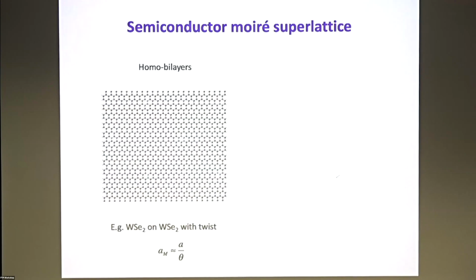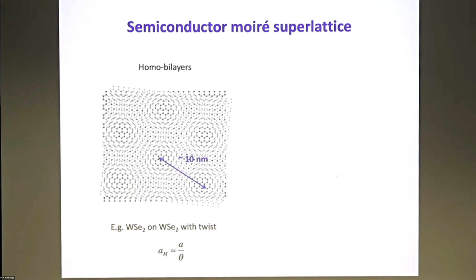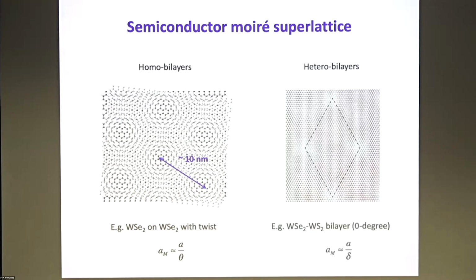Okay, so similar to twisted bilayer graphene, now very famous, you can produce moiré materials using the same kind of technique. For instance, you can just give it a twist angle, and you can generate a moiré pattern with period about 10 nanometers, depending on the twist angle. But 10 nanometers is the range that we are interested in.